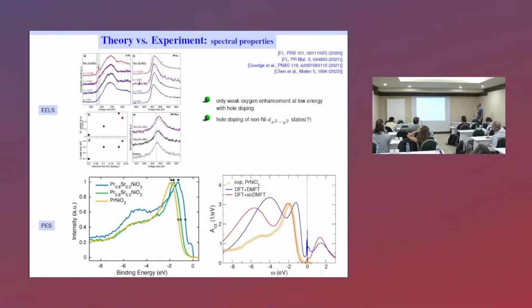As Carsten was already pointing out, if you now go to the doped regime, that doesn't match so nicely anymore. So then we would have claimed victory and said, whoa, we have the story. But for some reason, this doped curve looks a bit strange because you have 20% holes, and there's not much shifting in it. It's not quite clear how that even goes along with the hole counting. So there's something maybe missing, or more work has to be done, both maybe on theory and also on the experimental side. But again, this is the first one, and we desperately need more spectroscopy.